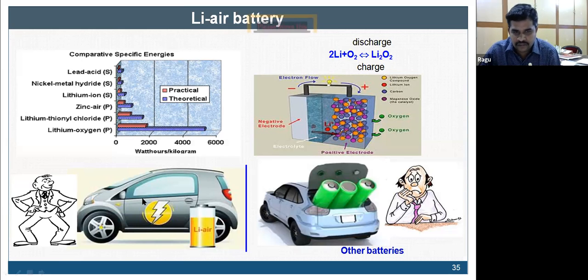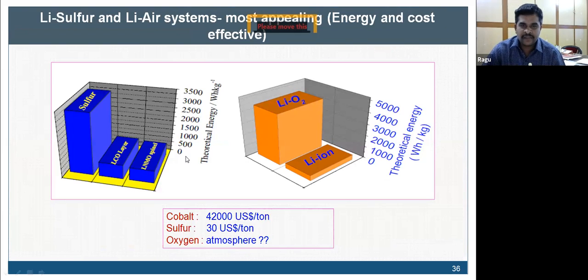And the energy density is also much higher. Look at this energy density scale. This is lithium air. Look at this, 5,000 watt-hour per kg. Now you can imagine how many times higher that is than your conventional batteries. Of course, lithium sulfur is also above 3,500 watt-hour per kg.